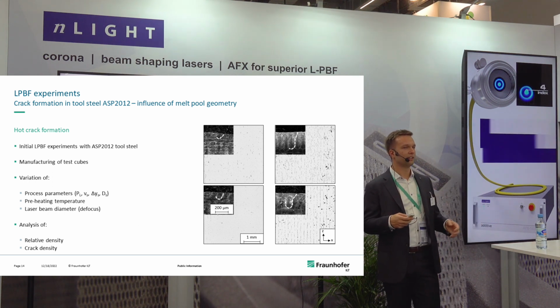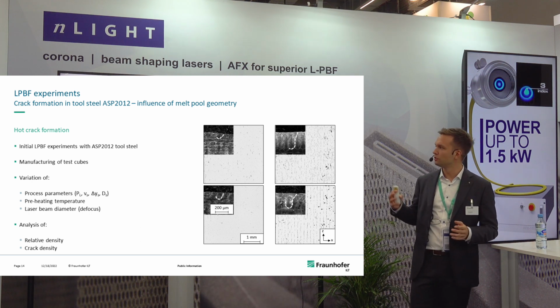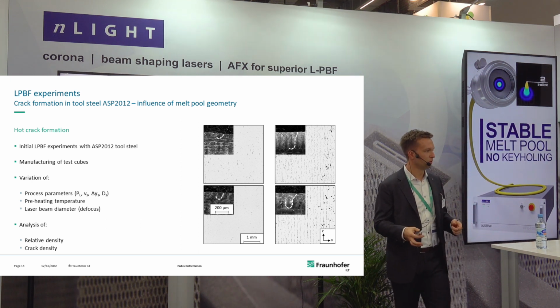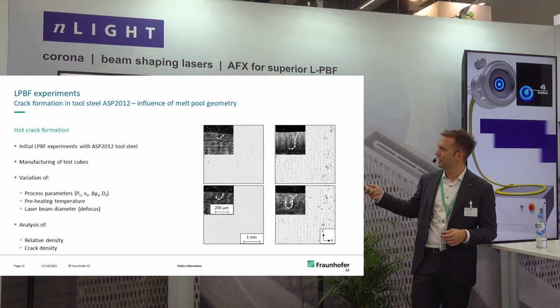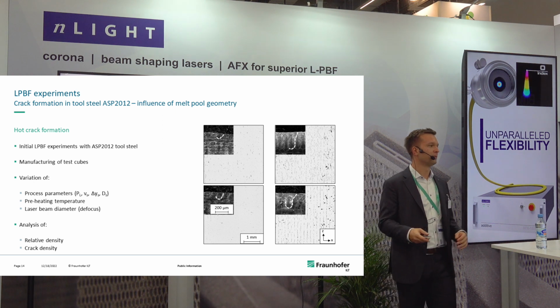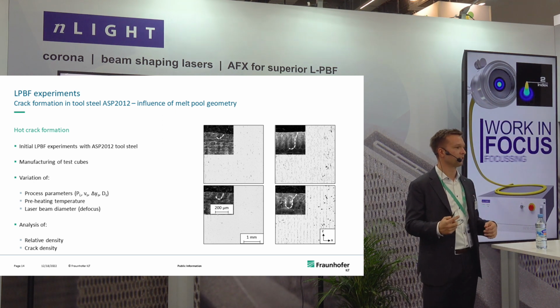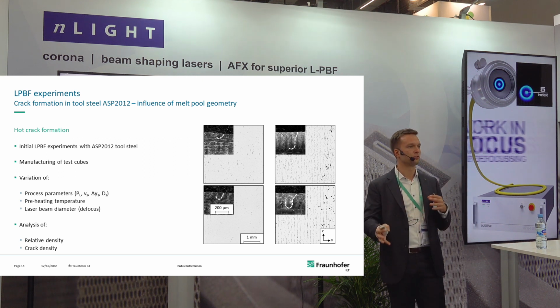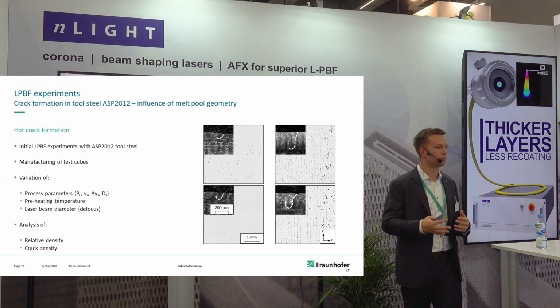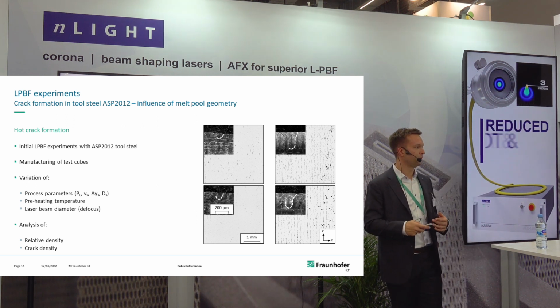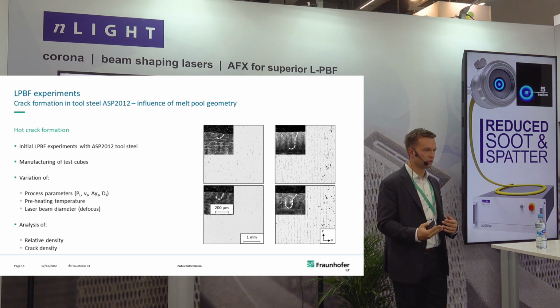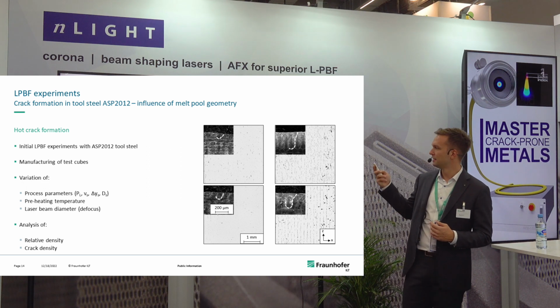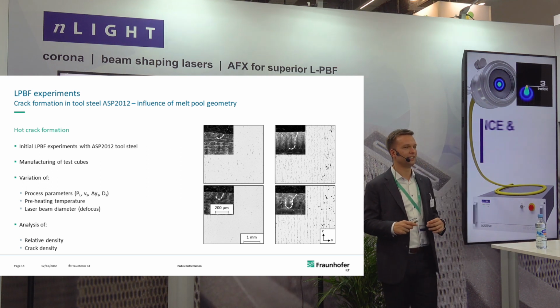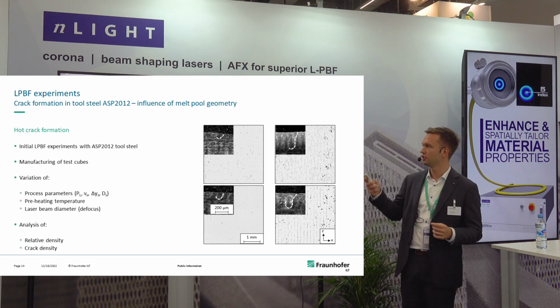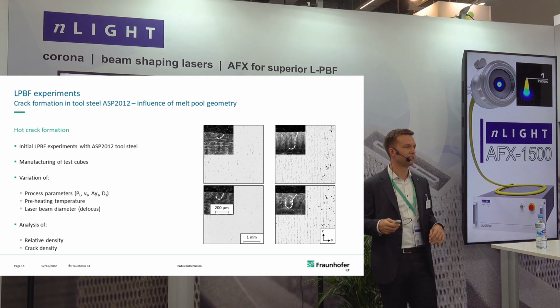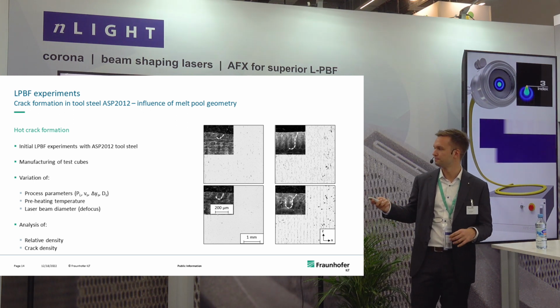So you end up with rather little crack, or next to no cracks, when you have a very shallow and wide melt pool, and you will end up with a lot of hot cracks, especially over several layers, when you have very deep and narrow melt pools that commonly occur in what we call transition mode welding, which is quite common for standard L-PBF processing parameters, because you continuously remelt multiple layers, and this is not necessarily good for inner stress buildup and hot crack formation, especially for this high-strength steel ASP 2012 material.